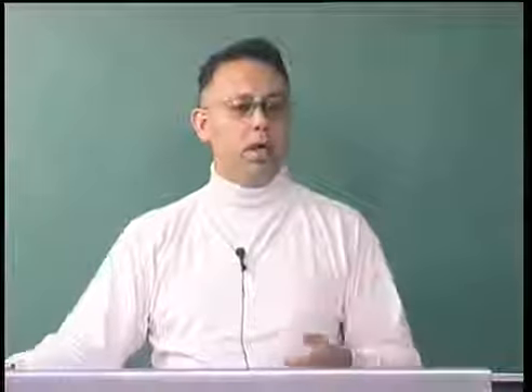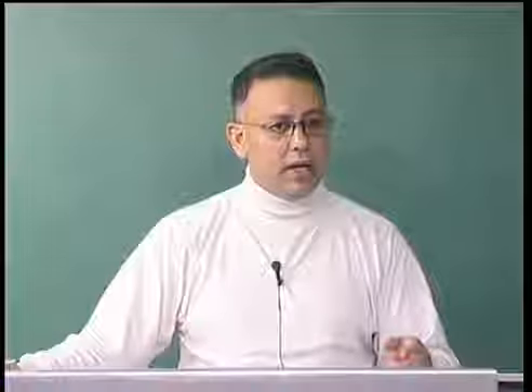He needs to go from, as we shall see soon, the atomic length scale to the length scale of the entire component, and this journey across length scales has to be integrated into a form which we in more common usage call the property of the material, which could, as we considered, be the ductility, it could be the fracture toughness, it could be the optical transmittance, it could be the electric polarization or polarizability, or it could be the magnetic susceptibility. So, there are very many properties which come about, and many of these can be understood by traveling across length scales and considering these factors.